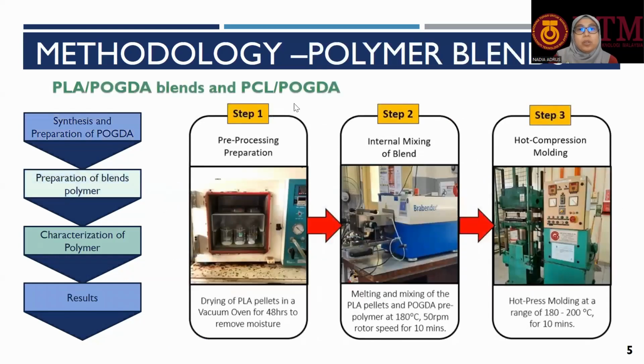Then we also would like to change the transition temperature for the stimuli by blending the POGDA with PLA, the common or the current polyester for SMP, and also with PCL. First of all, the PLA or PCL has been dried to remove the moisture. Then we use the Brabender to blend by internal mixing with the POGDA pre-polymer, and then hot compression molding in order to produce the shape of the sample.